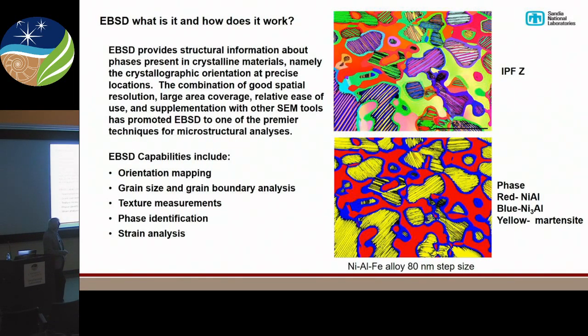Just some microstructures that I found really attractive. This is basically a nickel iron aluminum alloy. This is taken with 80 nanometer steps, so the resolution of that image is about 80 nanometers. This is a representation of the orientation of those phases within that microstructure. And down here, we've identified the phases by their crystallography.